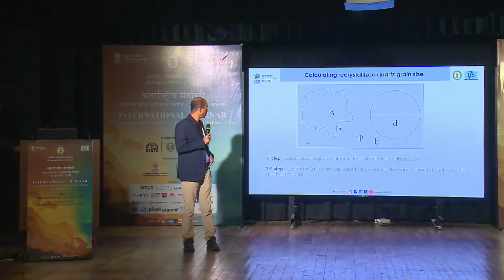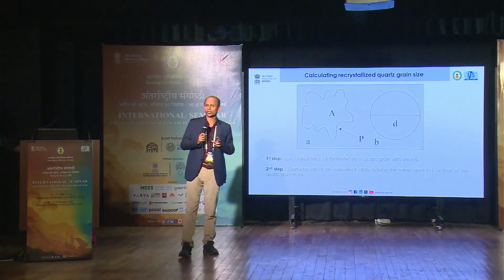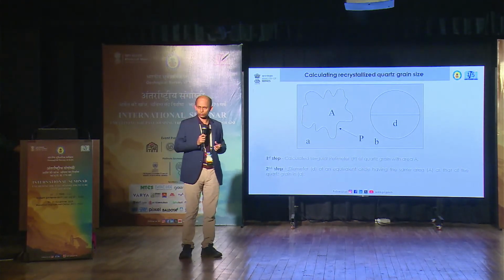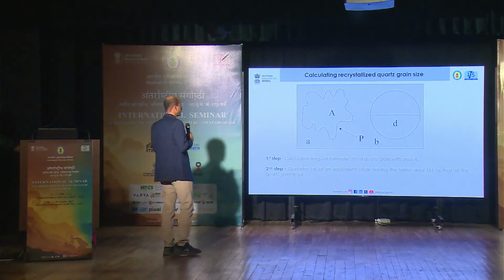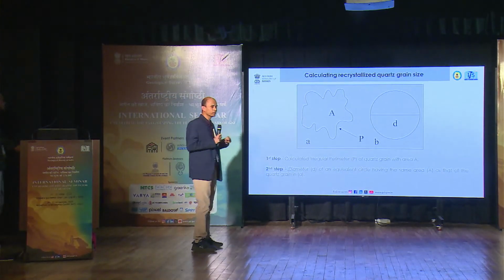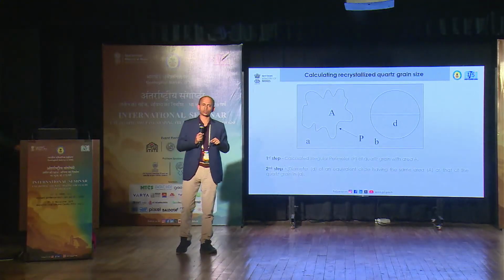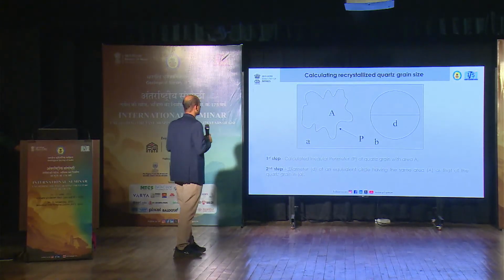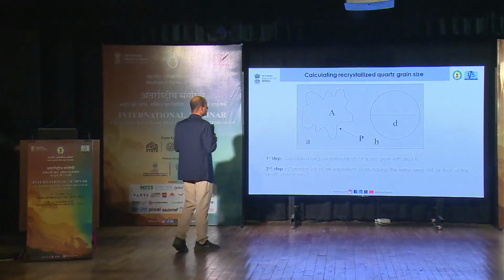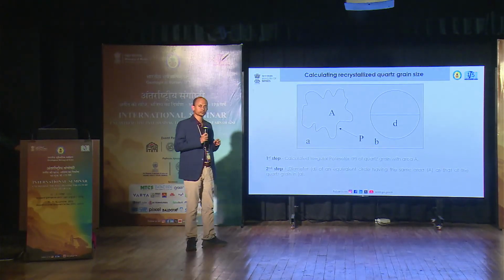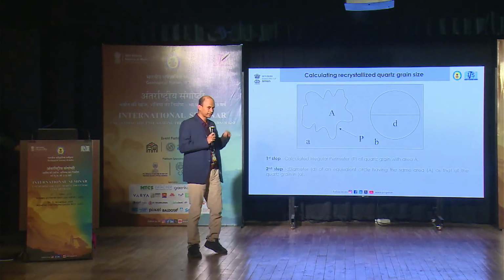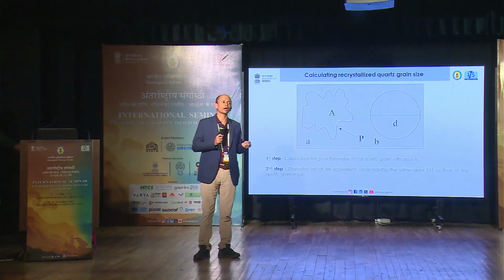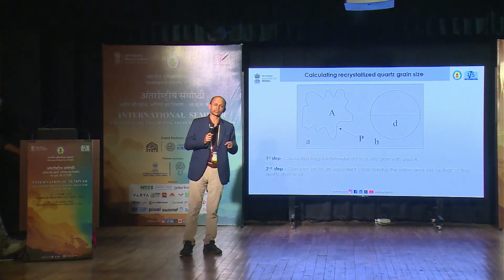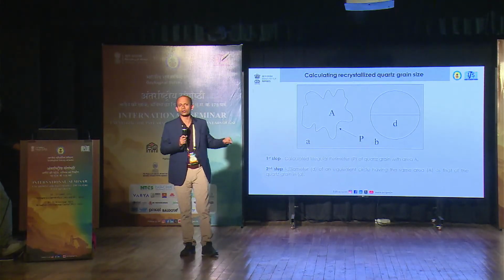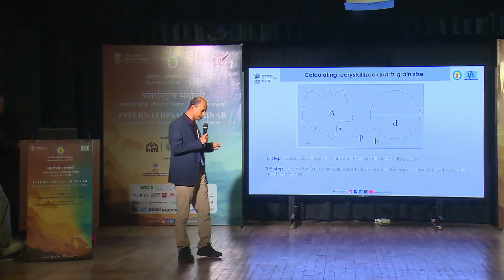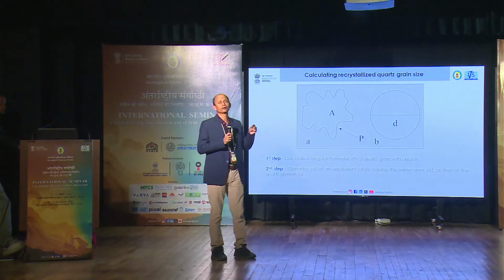Next. Okay, so before discussing the quartz microstructures, what we did was we calculated the diameter, or the grain size, of the recrystallized quartz grains. We very meticulously calculated the perimeter and area of the recrystallized quartz grain in ImageJ software, and then we found out the area of an equivalent circle with an equivalent diameter as that of the recrystallized quartz grain. That diameter gives us the recrystallized grain size.